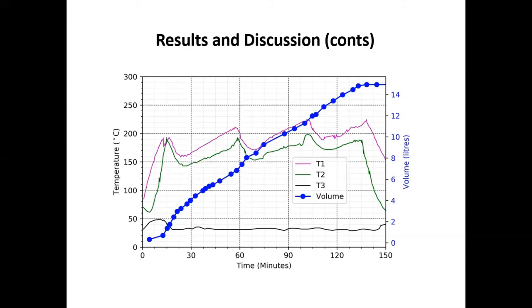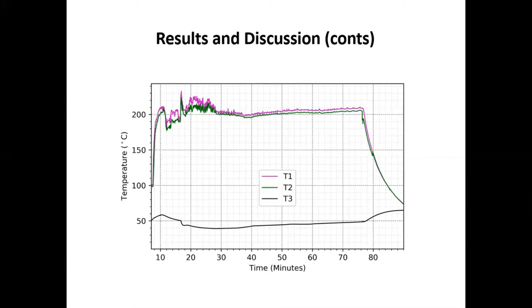So this was our first graph, but remember we need to charge it at around 200 degrees centigrade. So we increased and obtained a graph that looks like this, close to 100. But remember, our point is to charge at a constant temperature. So what we did, we used a valve which was partially opened to set the maximum flow rate to a lower value. And when we did that, we were able to obtain a charging temperature which is nearly constant at 200. Initially we had a fluctuation range of 50, but after 30 minutes, the charging temperature range was at around 14 degrees centigrade.